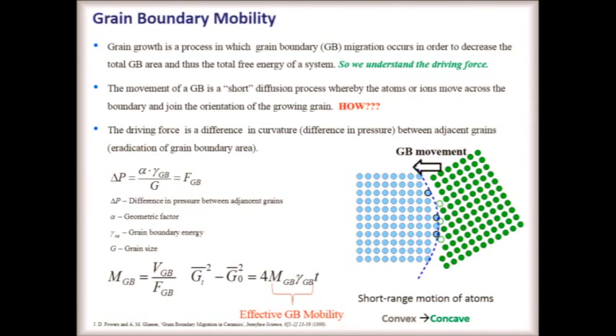So in this approach, which is just a parabolic model, and there are others which can be applied, the difference in grain size as a function of time will show us the mobility. The actual mobility is here, that's m, and it's multiplied by the grain boundary energy. And since I don't want to guess about grain boundary energy ever, I'd rather measure it. And since I explained that that's a problem to measure, we're going to leave these together and we'll just call it effective grain boundary mobility. So I'm measuring the grain boundary mobility for this mean ensemble of grain boundaries in the system, and I'm ignoring any changes in the grain boundaries as a function of time.